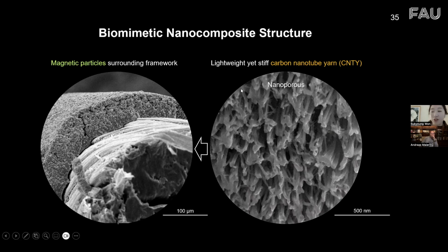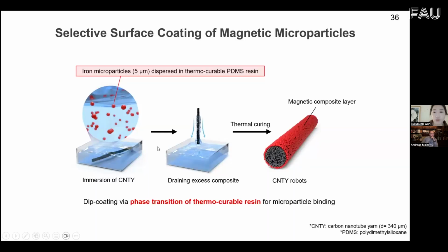This is made of twisting 100 carbon nanotubes into the yarn, and the magnetic microparticles were coated onto the surface of the microrobot for the magnetic attraction. These microparticles could not get inside the nanoporous structure of the CNT yarn framework, and for selective surface coating of the magnetic particles, we applied the dip coating process of the polymer composites. Based on the phase transition of the thermocurable PDMS polymer resins, these microparticles could be bound on the surface of the robot after the thermocuring process.